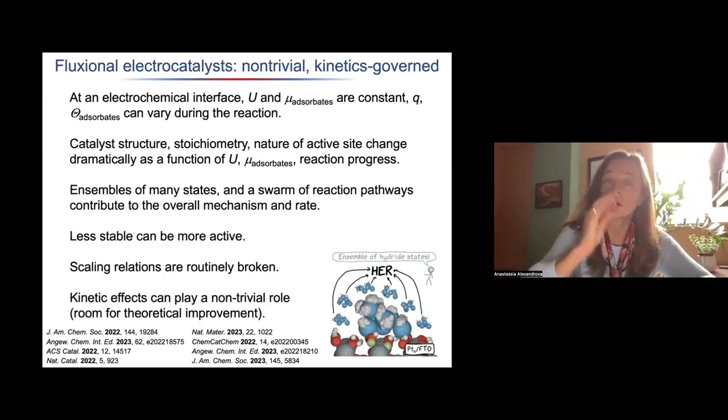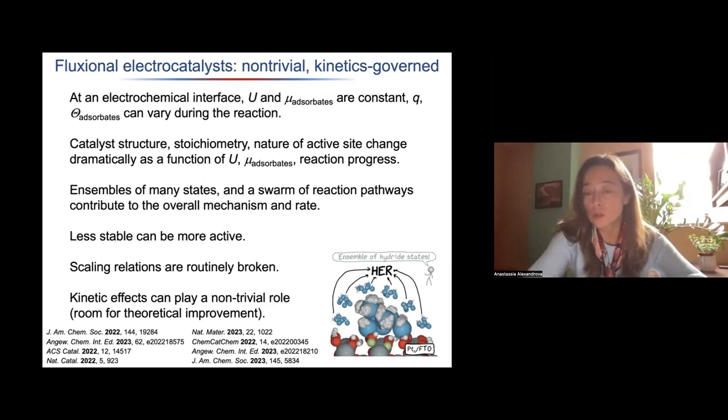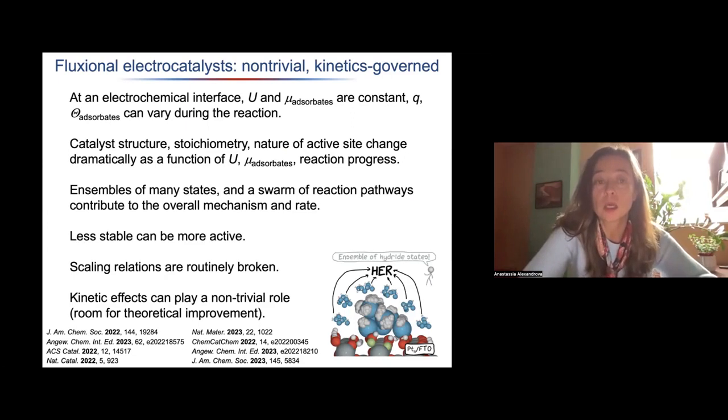Okay, as a summary, catalytic interfaces can be extremely fluxional, even electrochemical interfaces. We can have radical change of structure of the interface that depends on temperature, chemical potentials of relevant adsorbates, and also the potential. The nature of the active site may change as a function of all these conditions and slight changes of voltage. We cannot assume one reaction profile. There can be many, and they should be viewed collectively.